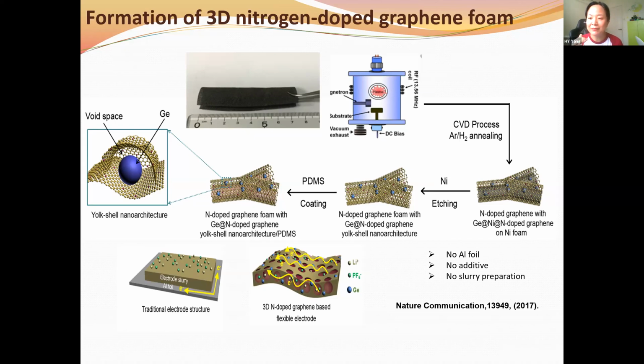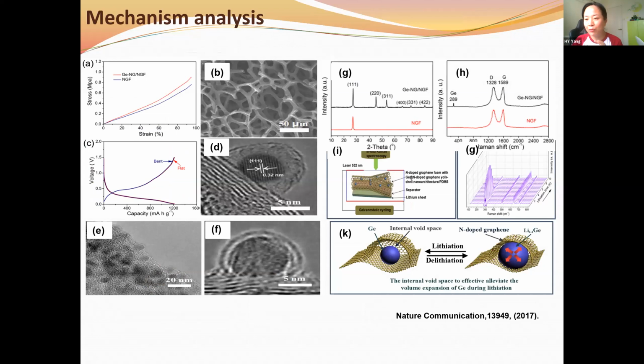With these three-dimensional lithium-ion batteries, the lithium ions can travel in three dimensions, X, Y, and Z, not only the X, Y direction. That gives us another degree of freedom for ion transport. We have also studied the volume expansion, because germanium has a 400% volume change when it is charged with lithium to generate lithium germanium. We observed that with the two layers of nitrogen-doped graphene, the void space is filled up when we charge the lithium germanium nanoparticles, and after we discharge, the void space is regenerated.